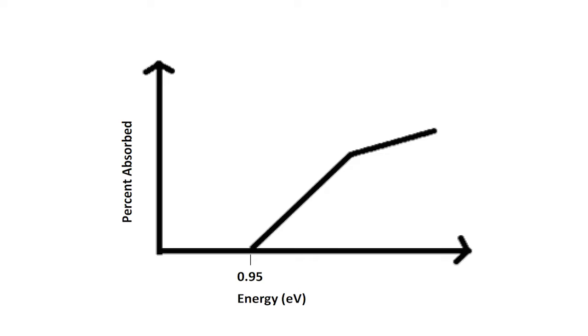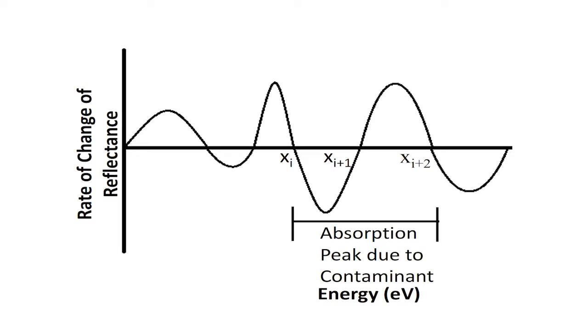I was able to show that it is possible to use a reflection spectrum of an iron pyrite sample to calculate bandgap. Since absorption below the bandgap is zero, reflection is constant below the bandgap and begins increasing after the bandgap energy has been achieved. By calculating the bandgap through optical testing, manufacturers can discard samples with the improper band structure. Previously, this line of reasoning had not been applied because researchers had assumed that contaminants would completely alter bandgap and absorption structures. I was also able to turn to computer modeling in MATLAB to show that any reflection peaks before the bandgap had been achieved indicate the presence of contaminants.